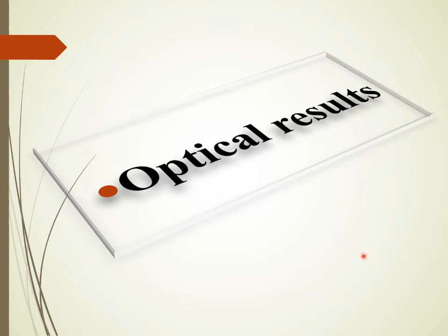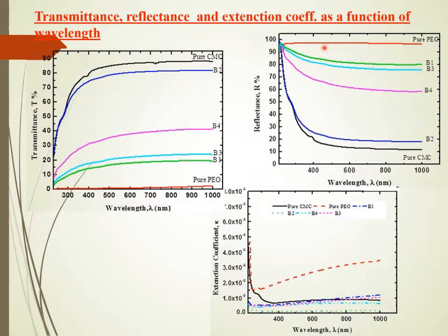Firstly, for the optical results, the following three figures present the changes that have occurred in the transmittance, reflectance, and extinction coefficient of pure CMC and PEO as a result of blending, where it is clear from the figures that the transmittance increased sharply with increasing wavelength until it reaches saturation in the visible and near IR region for pure and blended samples. Similarly for reflectance and extinction coefficient.